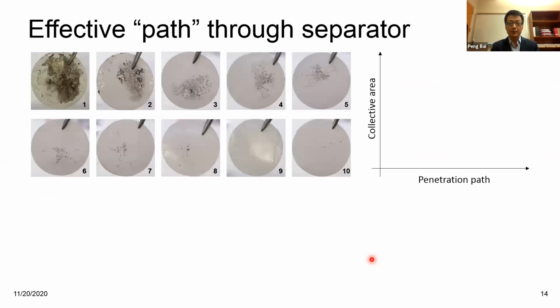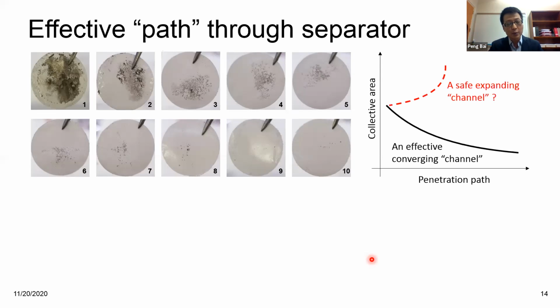So here, let's come back to what we did with the multiple separators. If you really quantify the dark area for each separator, you can see that we effectively form a converging channel along the depth direction. But what if we can promote the lateral transport so that the penetration will grow like this? You will have more pores being filled with this metal penetration, but eventually you will result in a much lower current density so that you will never trigger diffusion limitation. So this is actually currently the question that leads our current research.